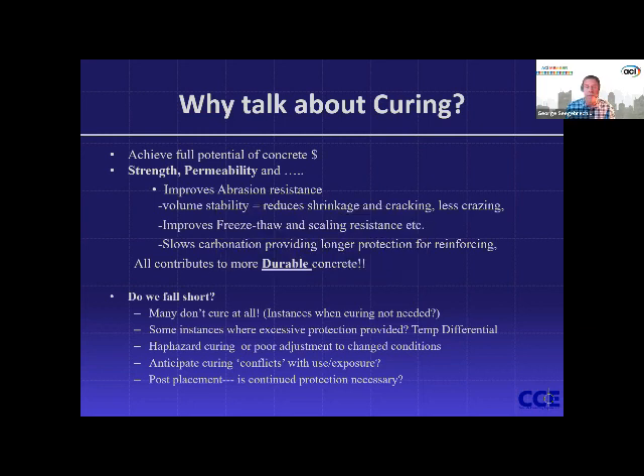So again, kind of a last slide, a summary. Don't overdo it on the protection. There are going to be some temperature ranges that ACI recommends for working, say in 305. Also, PCA's Design and Control of Concrete Mixtures will give them to you too. Tend toward the lower end of the range. If they say 50 to 70, 50, 52 is fine. Because don't forget, you're going to be going up with the heat of hydration bump after you get the concrete installed, for lack of a better word.